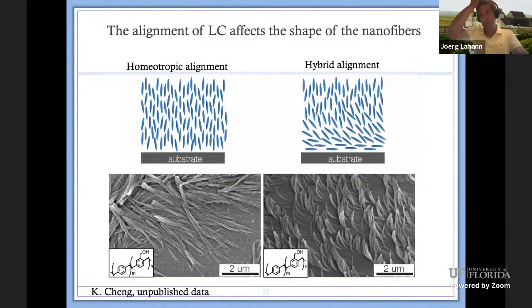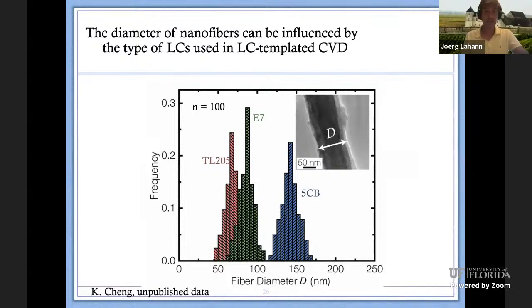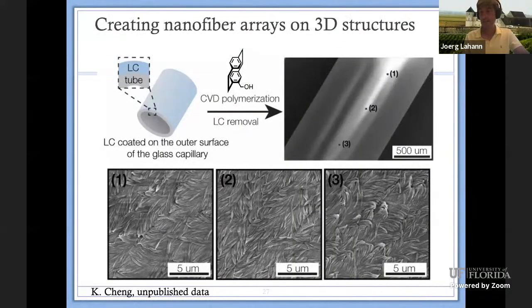So this is one way to control the alignment. One is homeotropically aligned LC, the other one is hybrid aligned LC, and you see very nicely that we do see a change in morphology of the fibers depending on the alignment of the LC. So that speaks towards the model that I described, and it's telling us we have some control over the shape indeed. Now, with respect to the diameters, I'm looking at different LCs. These are 3 different LCs with different elastic energies. And indeed, we can control the diameter as a function of the LC. In fact, it correlates with the elastic energy to some extent, at least.